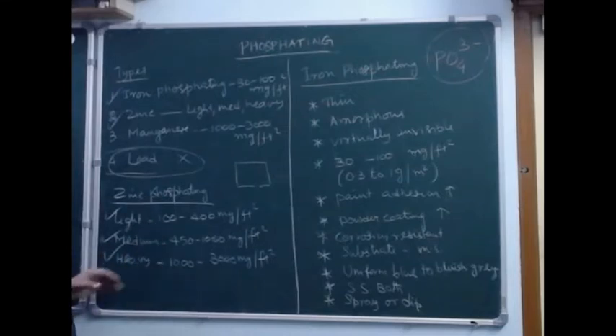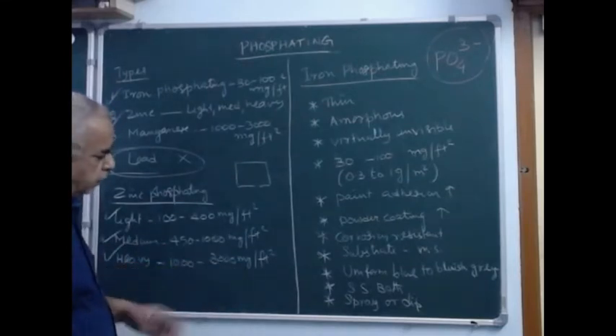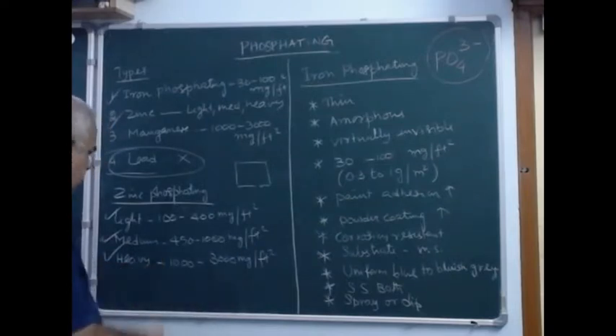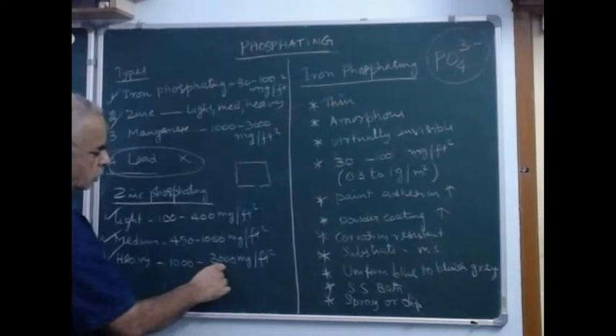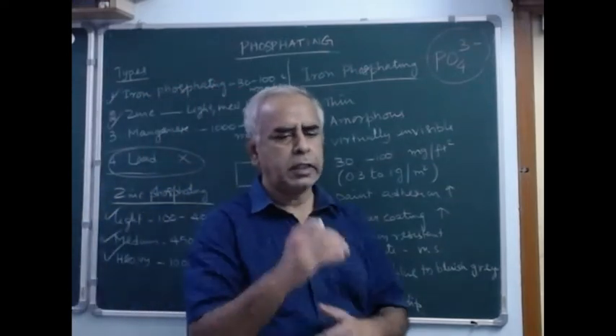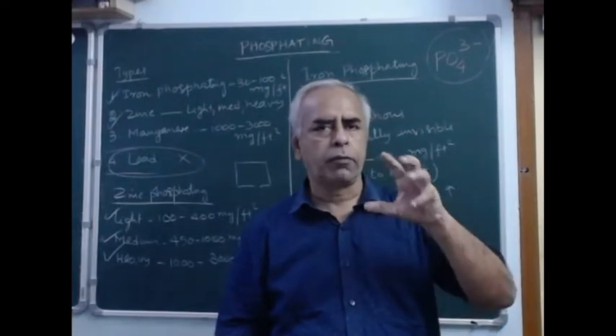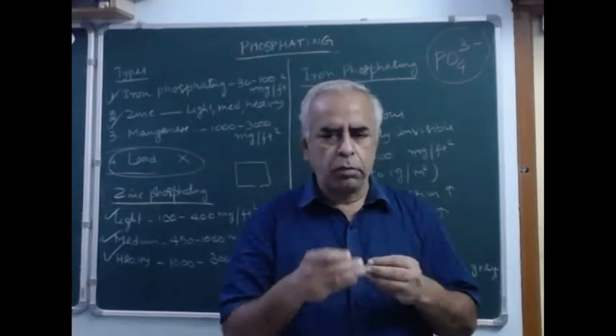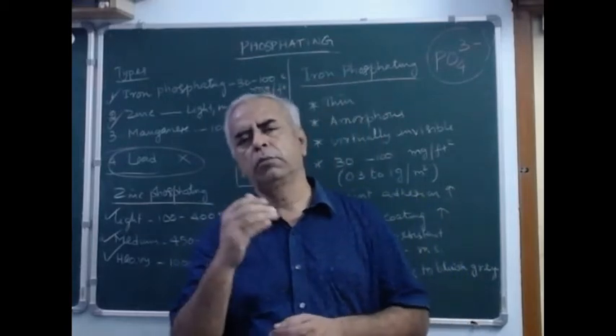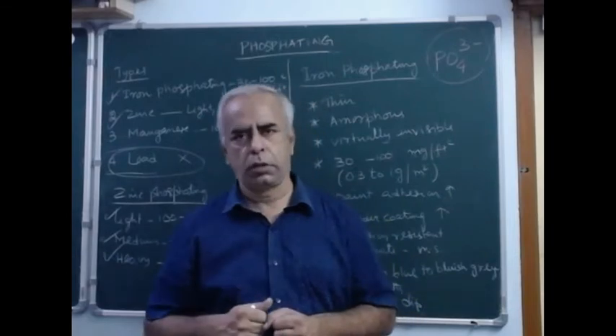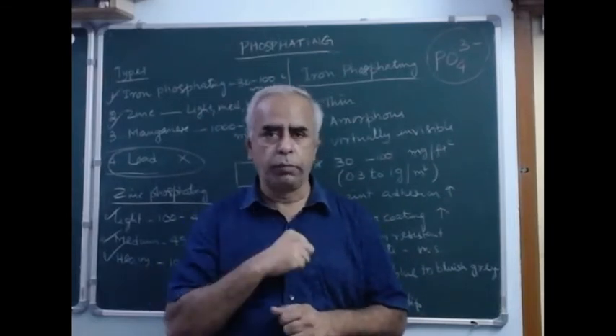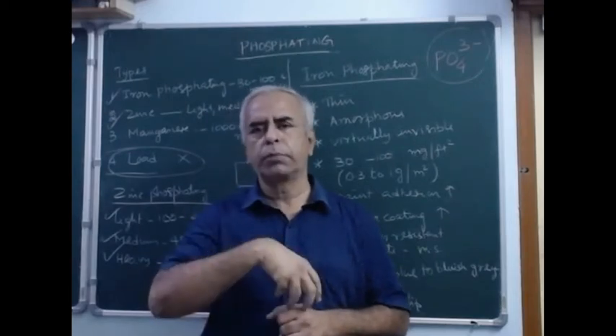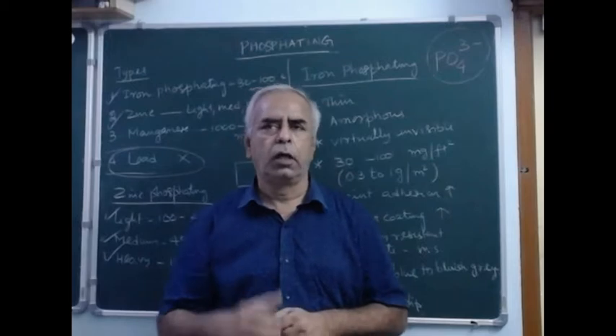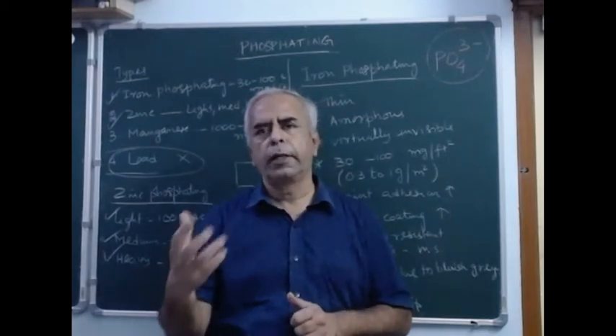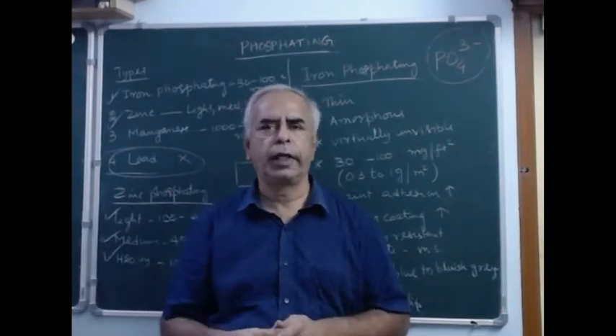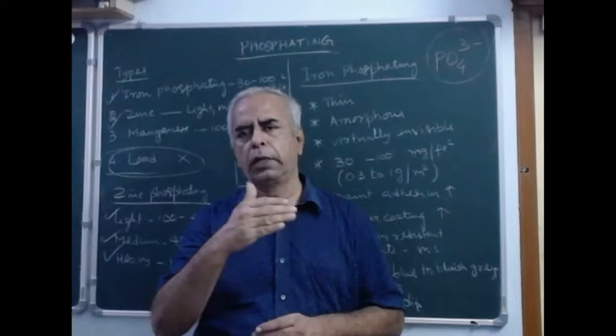Next, heavy. Heavy is intended generally for greasing and waxing, or tubing also. So heavy is 1000 to 3000 milligram per square foot. With the increase of coating weight, the coating roughness will be more, and there will be a lot of porosity also. If there is more porosity, that is not good for corrosion resistance. But at the same time, it can absorb the oil and waxes, and for that purpose heavy coating is recommended. For corrosion resistance, by painting, either by liquid paint or powder painting, you can go for light to medium.